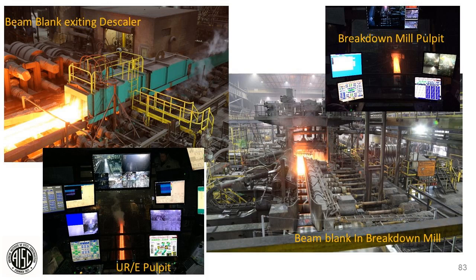And you can see a couple of shots of the pulpits here. In the upper right-hand side, we have a breakdown mill pulpit shot, and the lower left-hand side is a picture of the universal rougher edger pulpit. Now there are screens on here that denote the thermal imagers. Now Shane talked about vanadium and columbium, and also nitrogen. Those are grain refiners, and in order to optimize those grain refiners, we have to do what's called controlled rolling. That would be on the next slide, please.